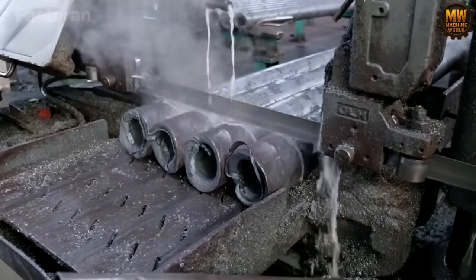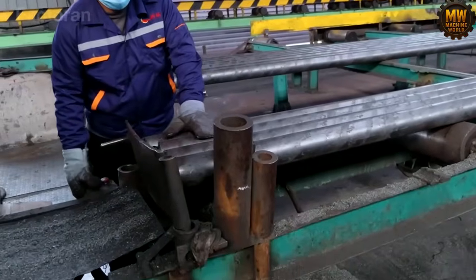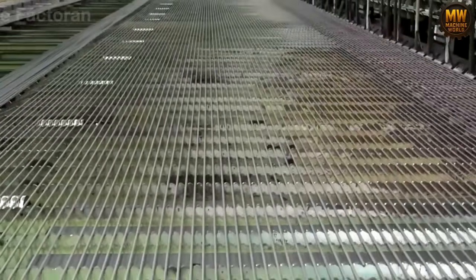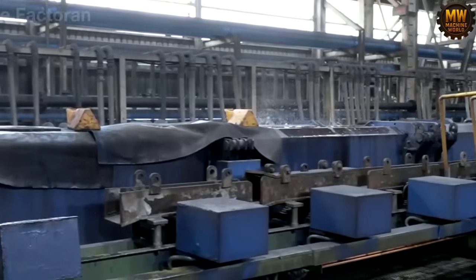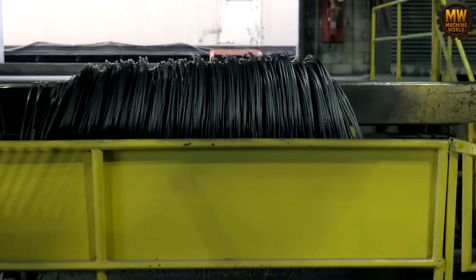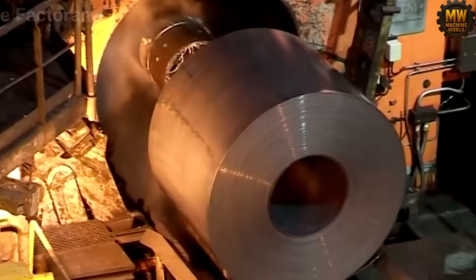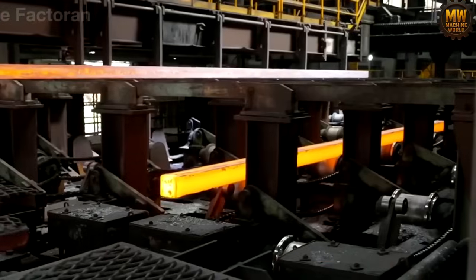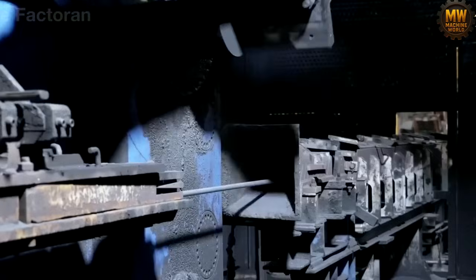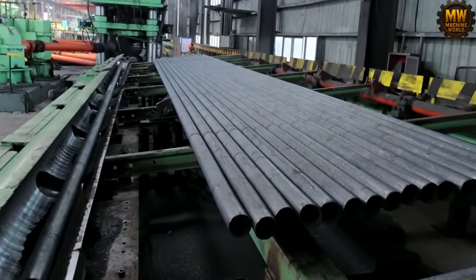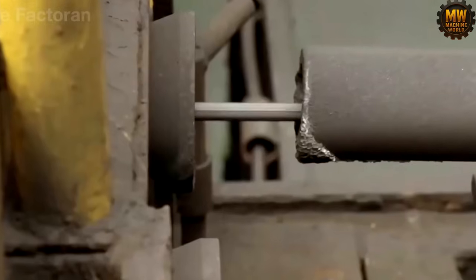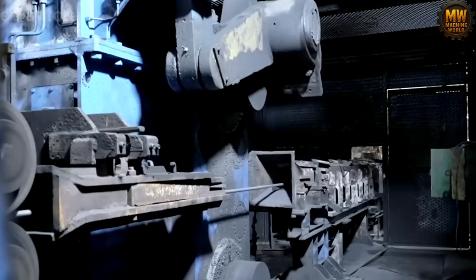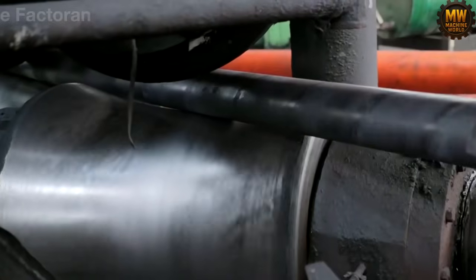But for a glowing coil to become a fully functional part, it must survive a zone of extreme thermal stress and paranoid control. The red-hot metal flies straight into a curtain of high-pressure water mist. Aggressive hissing fills the chamber. Steam explodes from the steel. The temperature plummets by hundreds of degrees in mere seconds, a thermal plunge violent enough to shatter ordinary glass. Instantaneous surface darkening follows. A cold, metallic gleam emerges on the outside, but inside, the threat remains. The freezing exterior of the hardened shell clashes violently with the still glowing, unstabilized core trapped within.